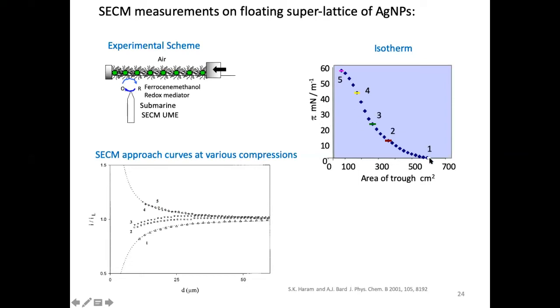Now what if I apply more pressure, or change the area of the trough? What will happen to the pressure here? This is the typical isotherm. The experiment is very simple, though quite complicated to perform. We applied various compression levels: 1, 2, 3, 4, 5. The film is getting more and more compressed, and we measure the SECM feedback from the film. Initially my film is not compressed.